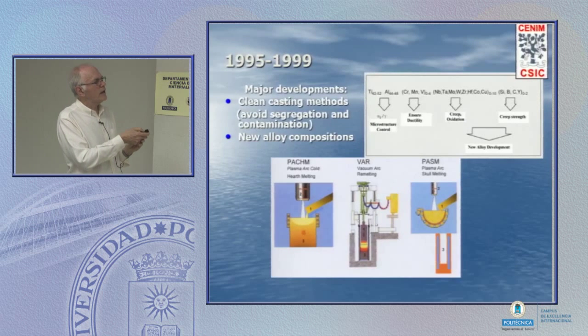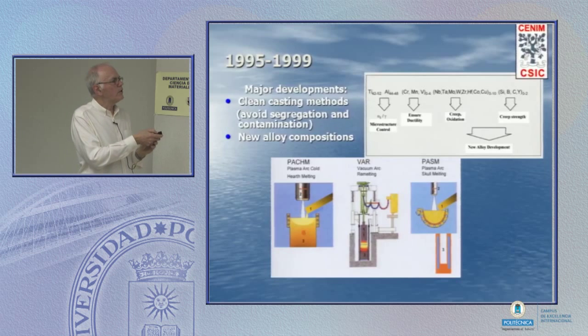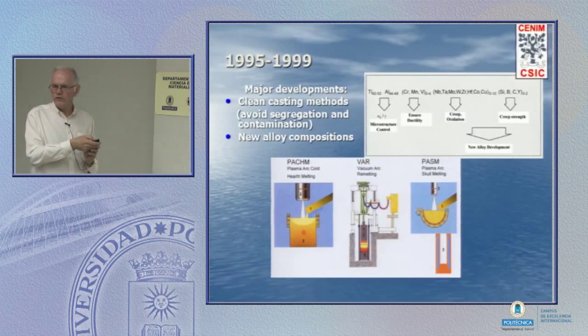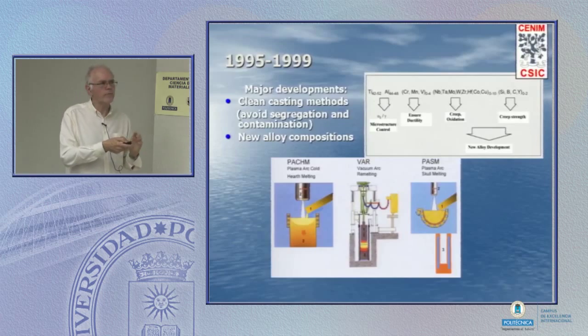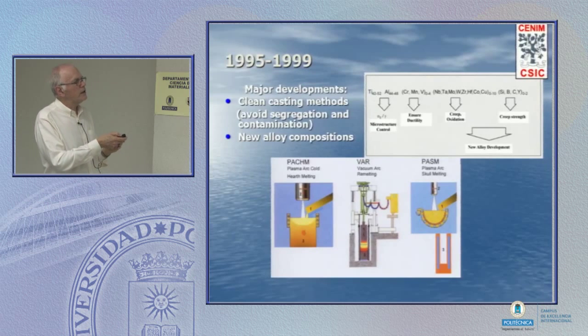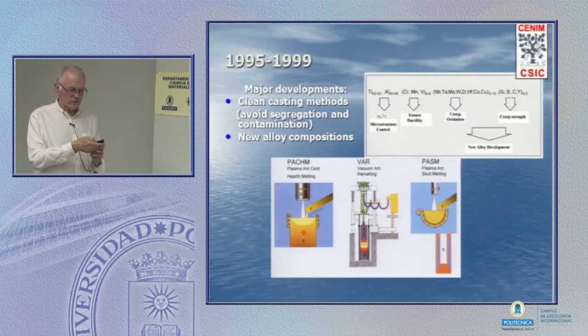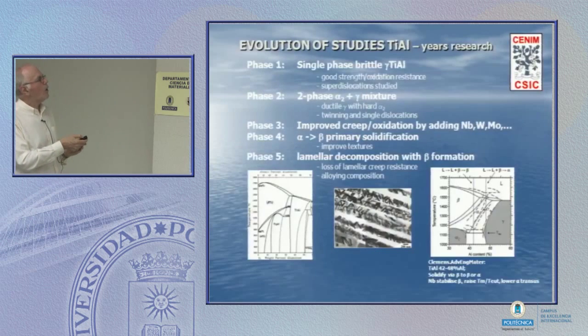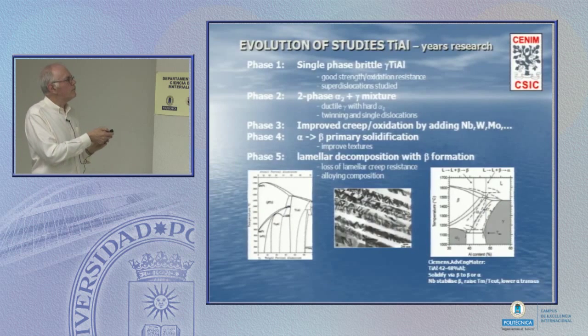Adding things like niobium, tantalum, molybdenum, we improve oxidation resistance because we want to use these at as high a temperature as possible. And then adding often interstitial elements, we improve the creep strength.